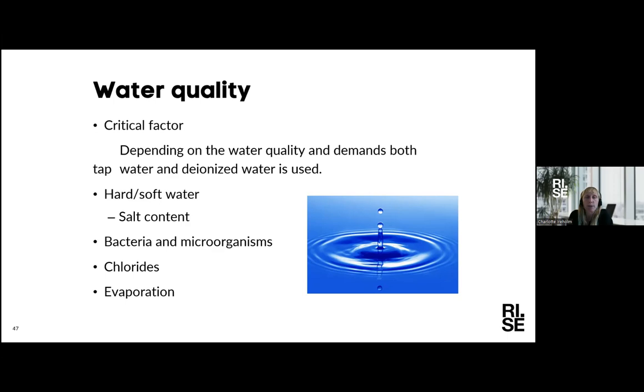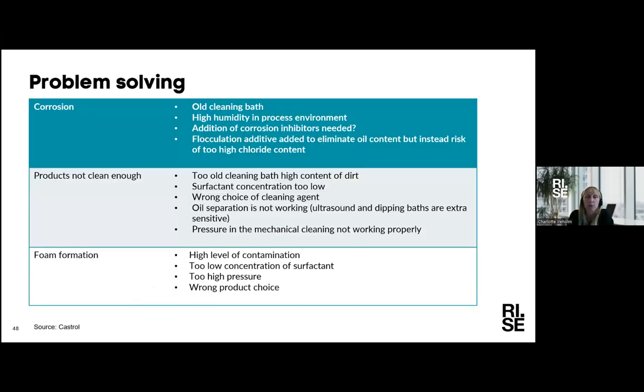So if we look at the next slide, what problems can occur? Corrosion is one, of course. If you have metal substrates, it can depend on the cleaning bath not being fresh, or that you have a really high humidity in the process environment when taking up the parts and sending them to the next process steps, or even in between process steps, cleaning steps, so to say. Normally you don't have one cleaning step, you have several in a series. Maybe you had to add some corrosion inhibitors or change the level of that.